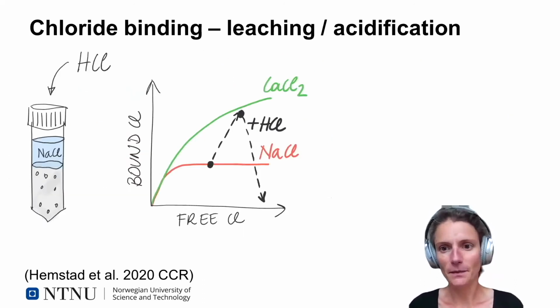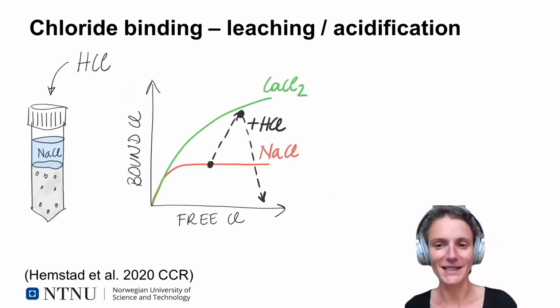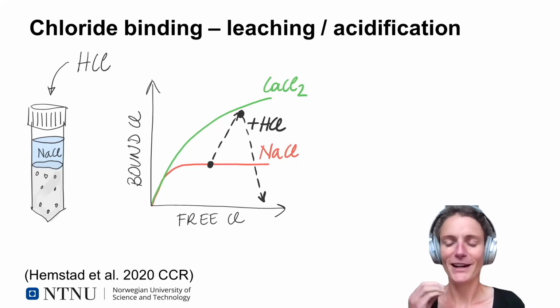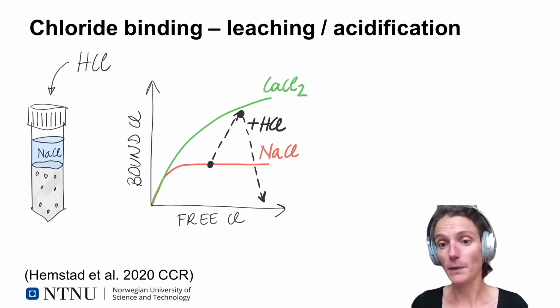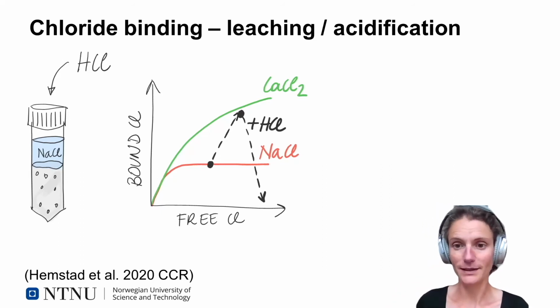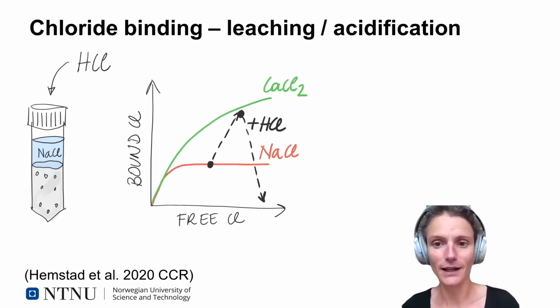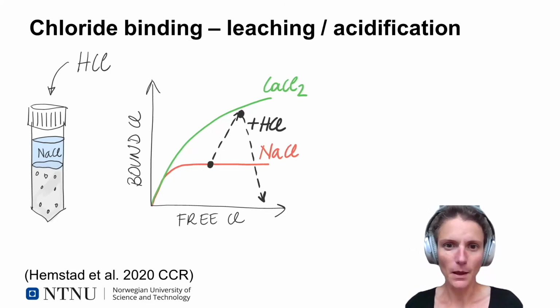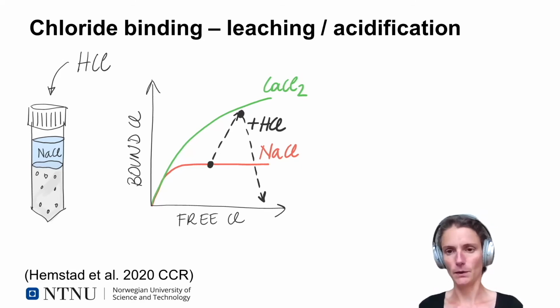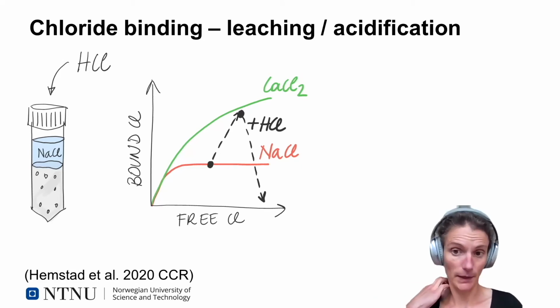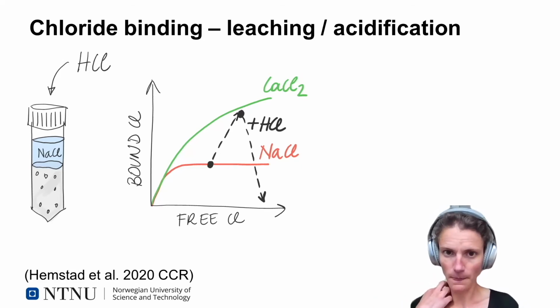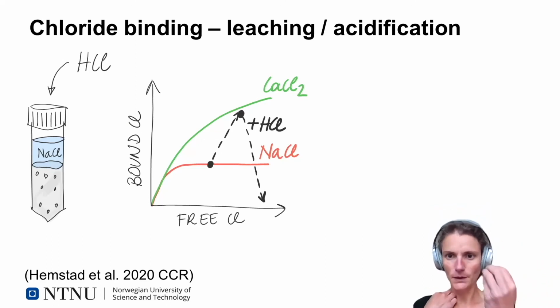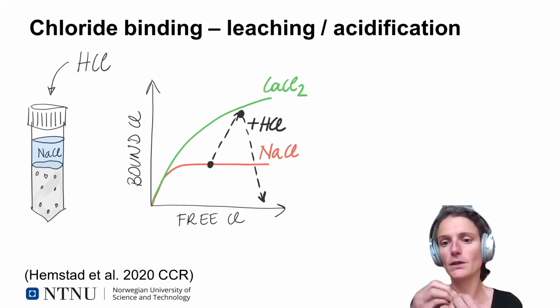So in this study, which I performed together with Peter Hemstad and Alisa Machner, we tried to play more with the effect of pH on chloride binding. So we call this the effect of leaching or acidification on chloride binding. What we did is we started with a sodium chloride and a calcium chloride binding isotherm, as we've seen before. But now we took a sample from the sodium chloride isotherm and we started gradually adding hydrochloric acid.